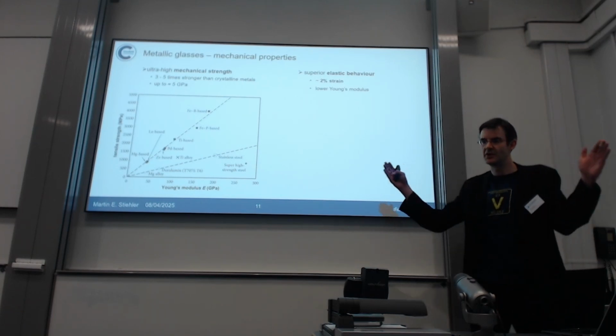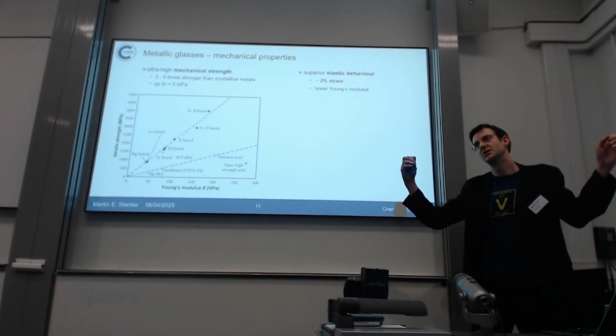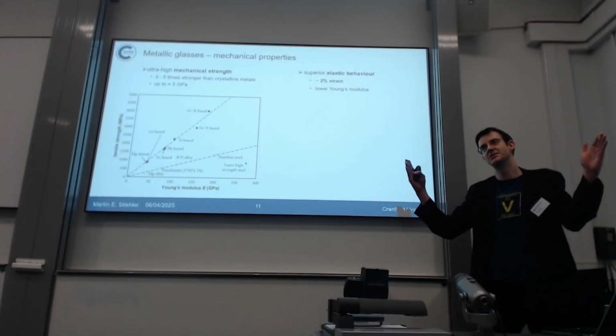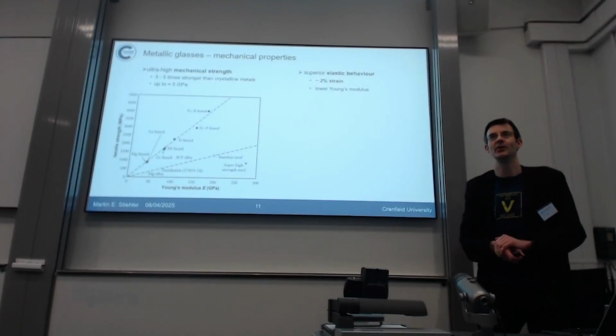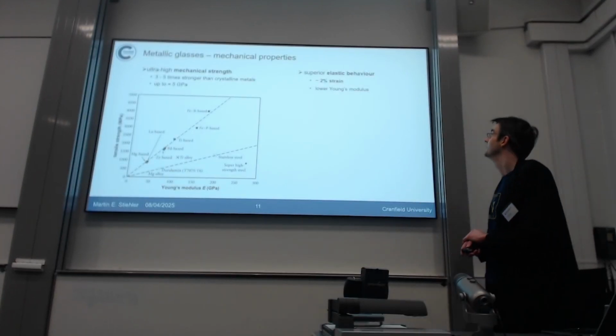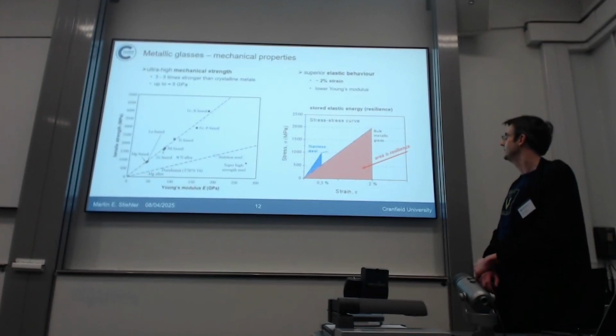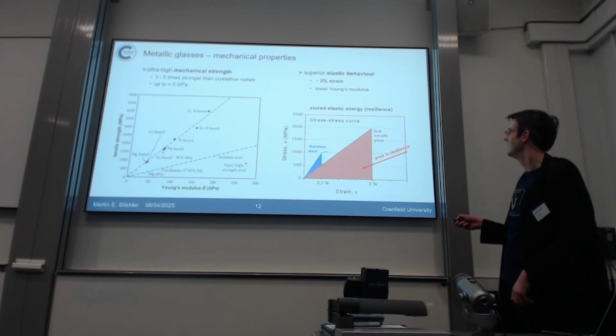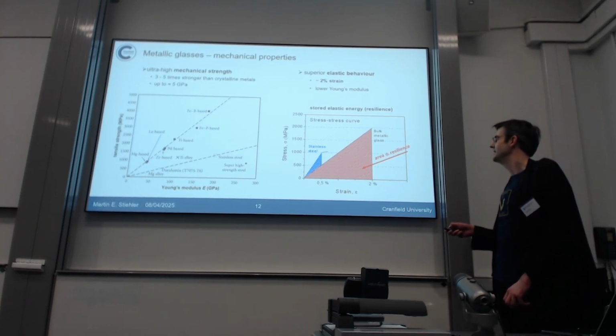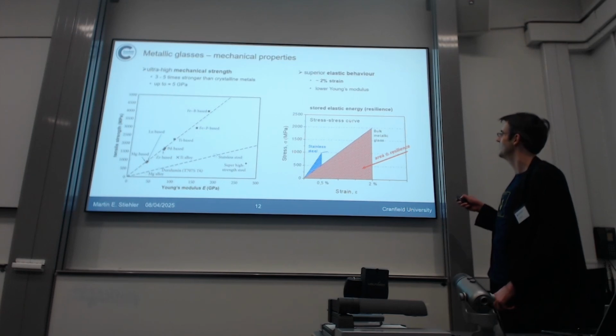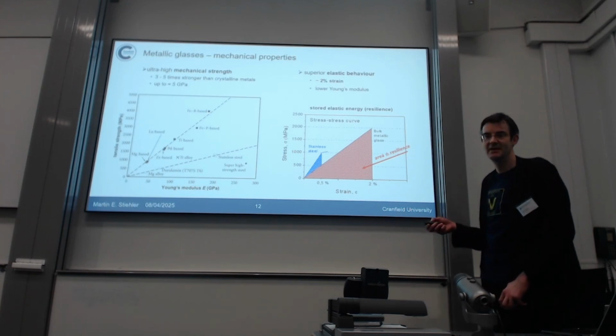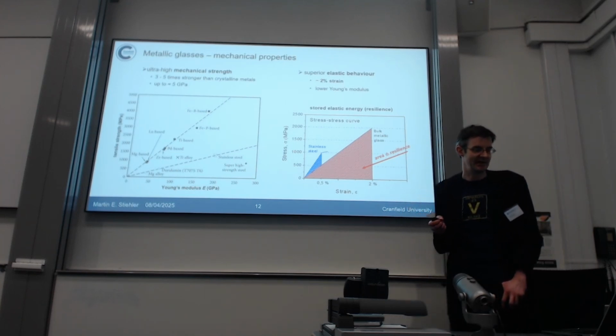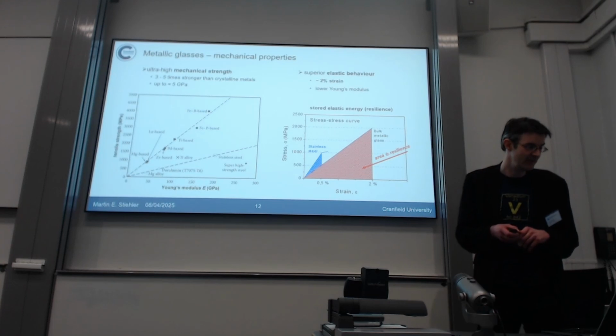Imagine you have a rod 1 meter long of a metallic glass. You could extend this by 2 centimeters or compress by 2 centimeters, and it would go back to the original shape without any plastic deformation. And you can nicely show this here on the stress-strain curve. There's a property called resilience, which is just the integral under the curve here. The Young's modulus is lower, that means the slope is lower, but the elastic limit is much higher, and that means this area is much bigger, and this corresponds to the energy that can be stored elastically in a material.